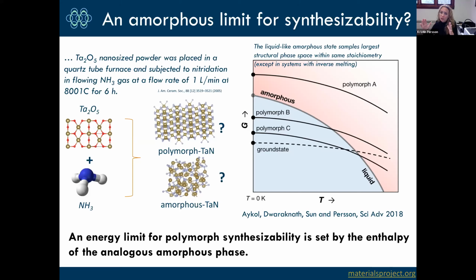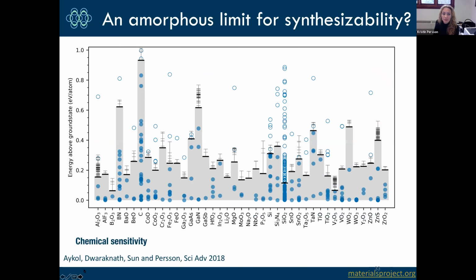So as you go up in temperature, you can see that polymorphs B and C, which started out with a lower enthalpy than the amorphous state, have a window of thermodynamic stability compared to the amorphous state. But polymorph A, which starts out with a higher enthalpy than the amorphous state, never has a shot, because it's always going to be thermodynamically unfavorable compared to the amorphous state, which now is kinetically as well as thermodynamically accessible. So we're hypothesizing that an energy limit for polymorph synthesizability is set by the enthalpy of the analogous amorphous phase. So let's test that. And we did.